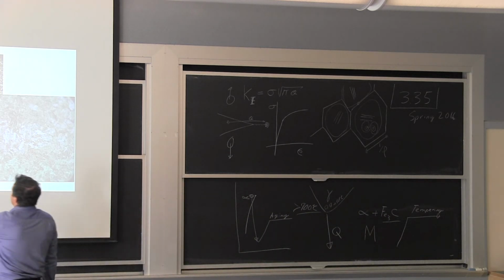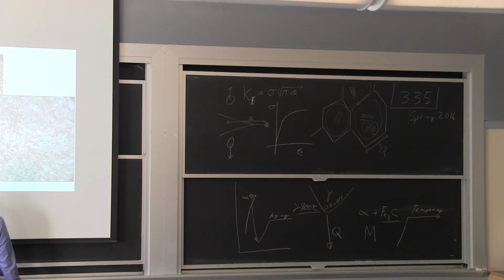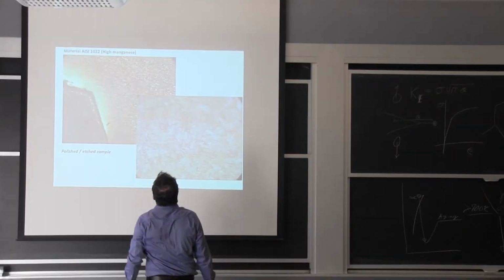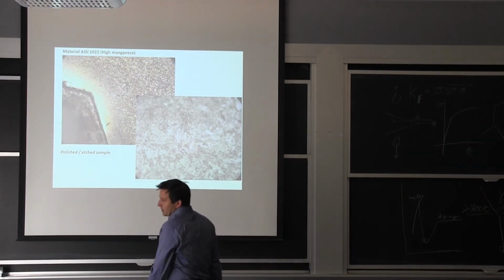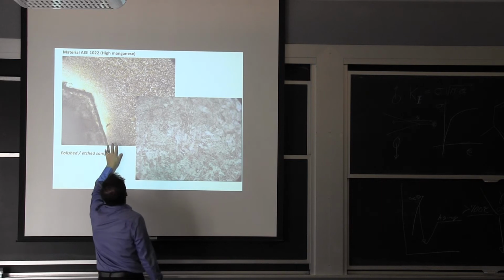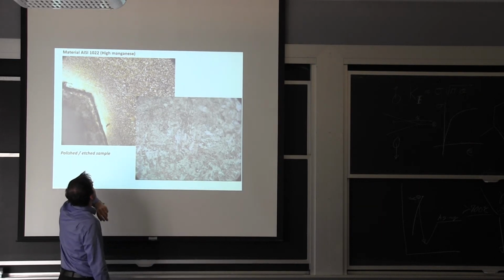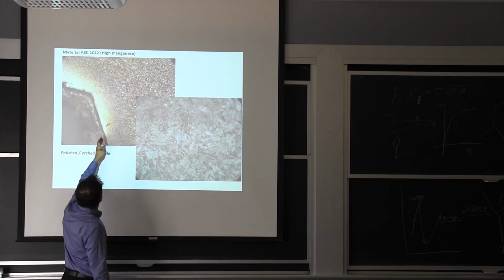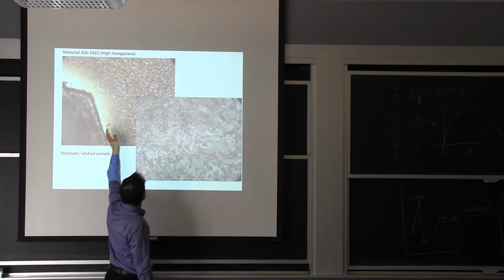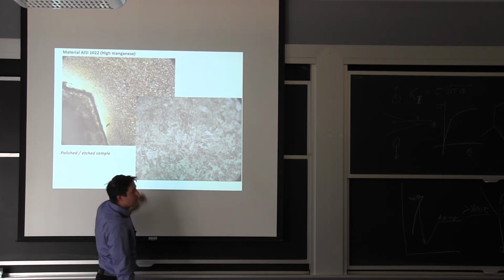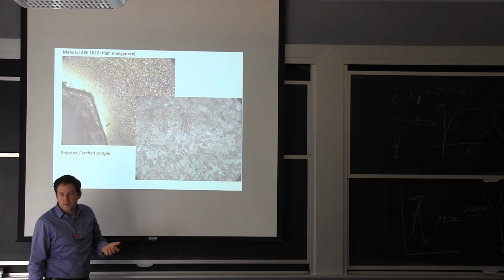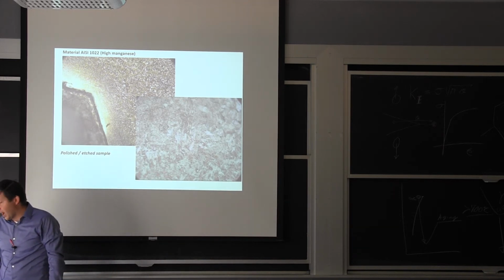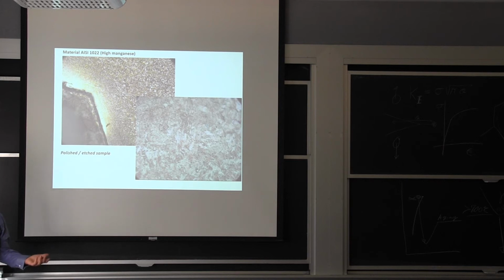This is what you see on the surface. It's really dark. It's hard sometimes. This is somebody who was learning polishing, so it's not the best polishing job, but it's something that needed to be done very quickly. We needed to know what was going on. You're looking at this layer here. It's about 200 micrometers, and you can see the very fine, darker microstructure. So this was carburized, and I didn't know it until we cut and polished it. It's not information that's necessarily available to the end user.